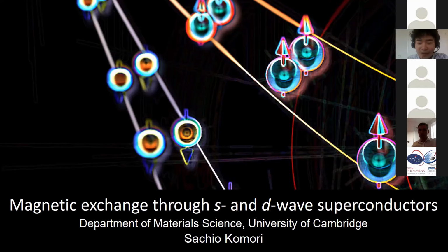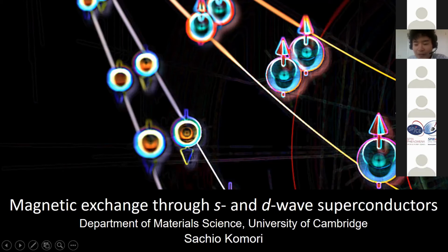And I think everyone here knows, but magnetic order, the exchange field, can penetrate into a superconductor, and that can potentially create unconventional superconducting states like spin polarized triplet superconducting states. And also, the order parameter of a superconductor can penetrate inside a ferromagnet, and that can potentially modulate magnetic properties. And today I would like to talk about this kind of nanoscale exchange interaction at superconductor ferromagnet interfaces.